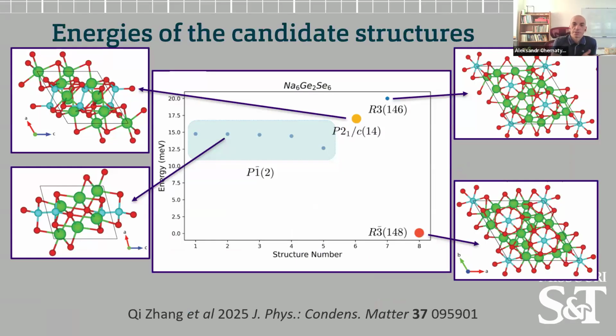I'll show the results here, because this is also a situation where we found a different structure from the one which was found experimentally. Experimentally, the system was considered some long time ago. There is a single paper which presents XRD and shows the solved structure, and it is claimed to be crystallizing in space group 14. We actually found that structure as well throughout our simulation, but we also found a structure which is significantly lower in energy. So we have run a whole bunch of simulations trying to see what kind of different properties this has, whether it has more interesting properties or not. And I think, honestly, in the grand scheme of things, it doesn't have anything particularly more interesting, but it is a significantly different structure.